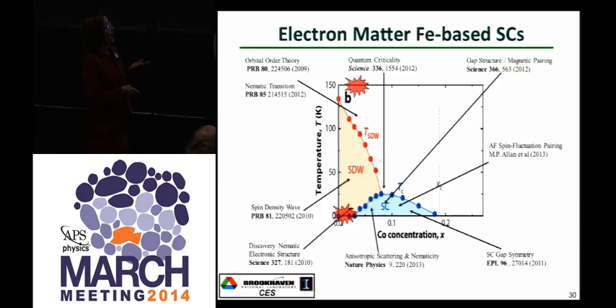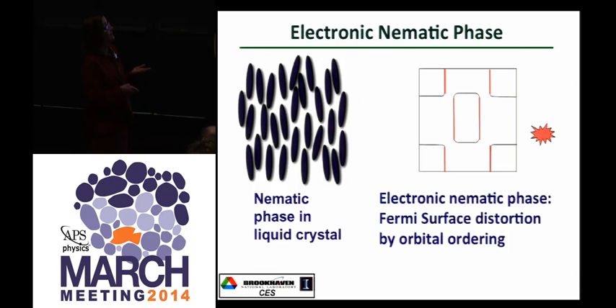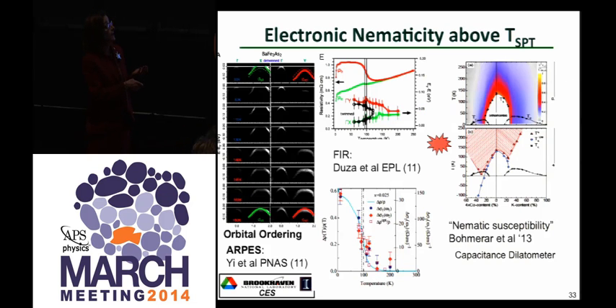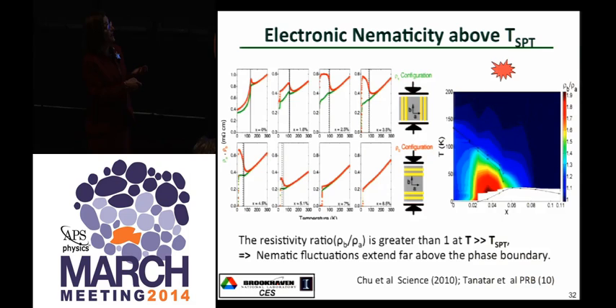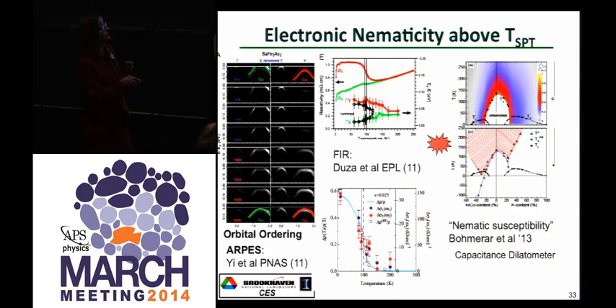And in the iron-based superconductors, we have the nematicity. A nematic, this is liquid crystals, and you can get a Fermi surface distortion that also breaks the C4 symmetry. And here's an example when it was first discovered by transport, that above the structural phase transition, you can force a kind of orthorhombicity.